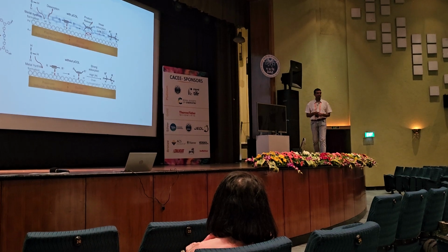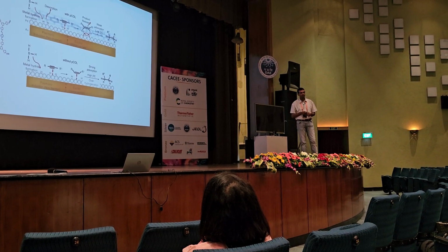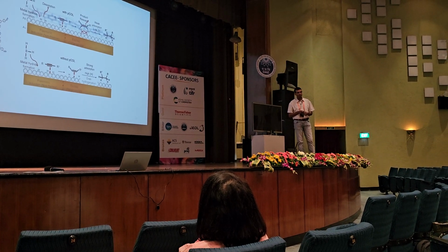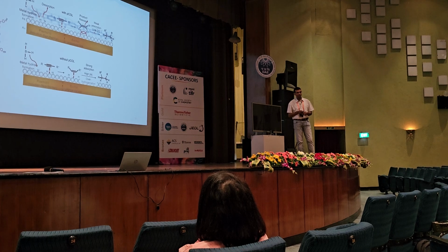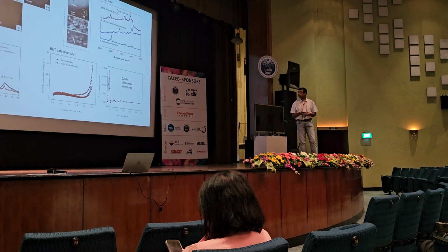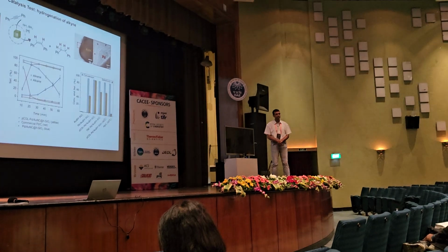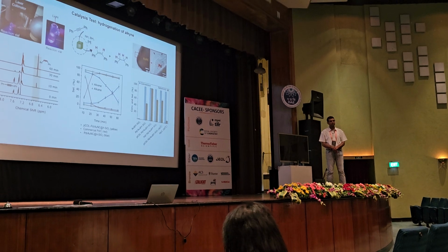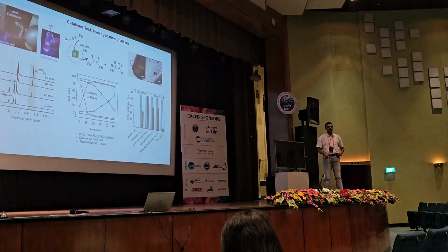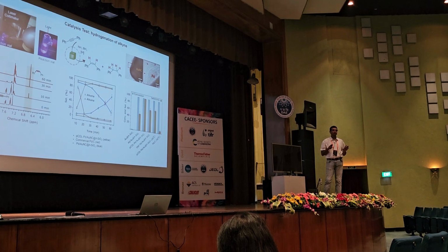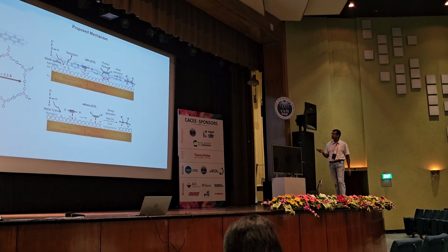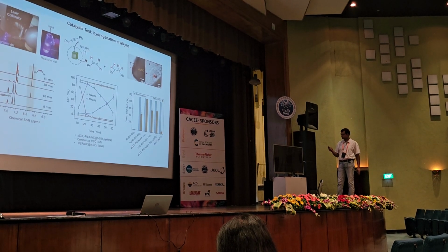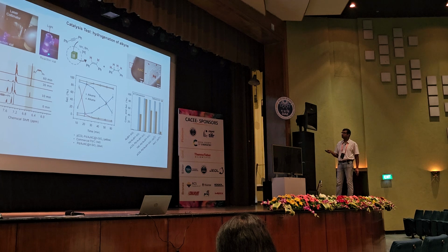Any other question? You make a polymer layer on the nanoparticle, and you told us that you are not using another monomer, rather you are using diol and converting it under light. I understand that. This happened in the presence of superoxide, yes. So how are you controlling the formation of the layer? Are you doing it at room temperature or at high temperature? We always maintain the temperature below 20 degrees Celsius. When you shine the reaction with light, there is a possibility the temperature may actually increase, so we control it.